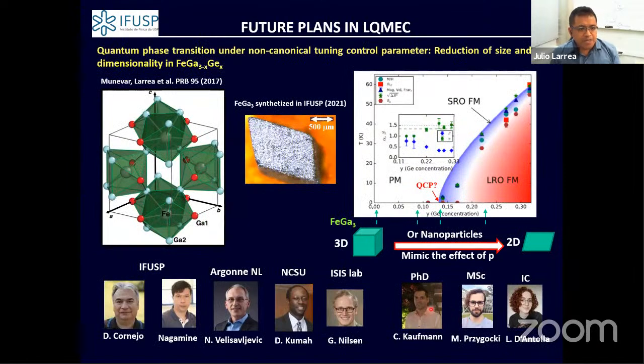Something else I wanted to share with you is that in addition to the non-thermal control parameter, we can also do something else, right? As a tuning control parameter, there is a very interesting idea to tune a quantum phase transition by another non-canonical tuning control parameter, for instance the reduction of dimensionality from 3D to 2D, by synthesizing thin films, or from the bulk 3D reducing the size of the system, producing nanoparticles. In both cases, in principle, we can mimic the effect of pressure.